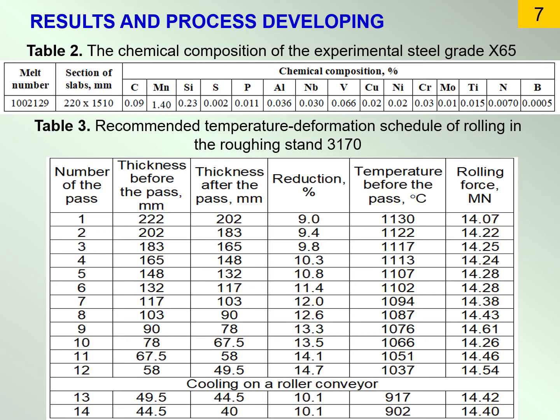The first stage of the rolling is carried out in the upper part of the austenitic area in the temperature range from 1130 Celsius degrees to 1020 Celsius degrees, with a reduction of more than 10% per pass. The last 2 to 4 passes are performed in the area of recrystallization inhibition in the temperature range of 920 to 880 Celsius degrees, with a reduction of 10%. Implementation of the rough rolling in stages promotes the formation of smaller austenitic grains and a more dispersed and homogeneous inherited ferrite structure in the finished rolled products. The recommended temperature deformation modes of rolling through the passes in the stand 3170 are given in Table 3.